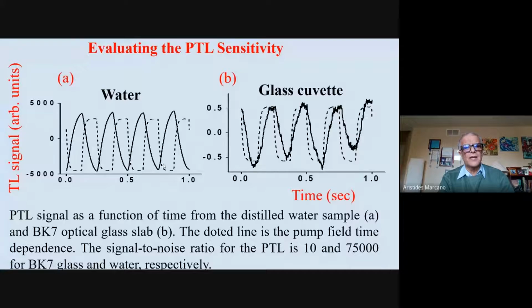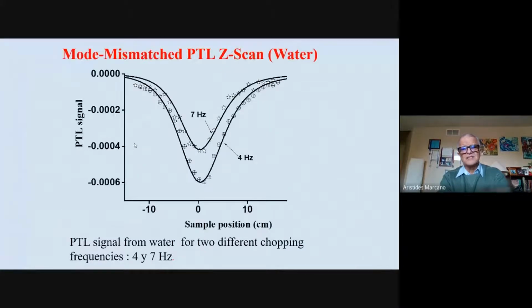You have this wave. And then we noticed that you have something from the cuvette itself. So the method is so sensitive that you can get signals from the cuvette, which are positive, but actually it can give you the evaluation of your signal to noise ratio, which is about 10 times here. So you multiply, and you have a signal to noise ratio for the water experiment of 10,000. Some people say that it is difficult to believe, too good to be true, but that's the real experiment we did. It's published. That's the real time evolution for water. You can see it's very nice, even though the signal is really small.